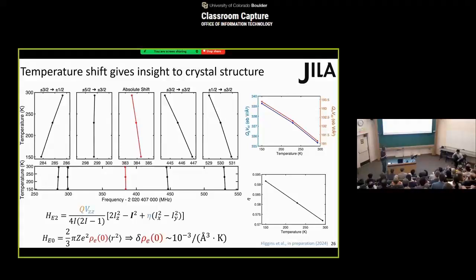Take that to mean that you're essentially changing the temperature, which changes the quadrupole electric field experienced. And if you take the appropriately weighted average of all these transitions, you become insensitive to the quadrupole interaction, but you become sensitive now to the monopole interaction, because the ground and excited state charge radius of the nucleus is different, so the charge density still changes things.